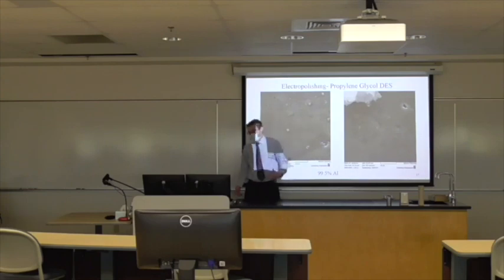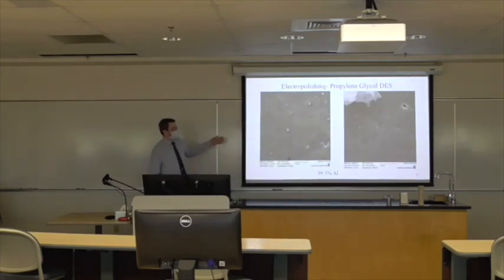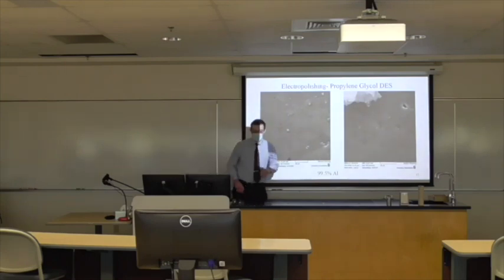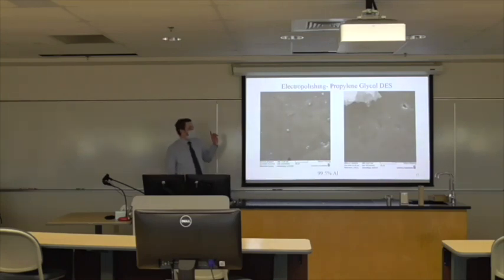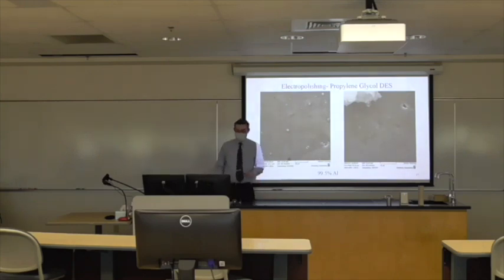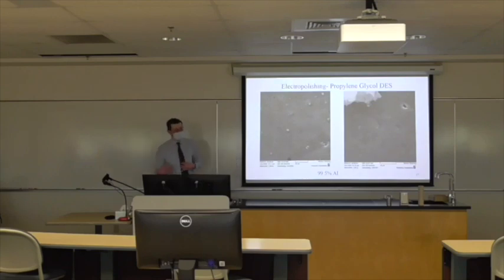Now this polishing, although there are still some defects, you could compare to the Brytal electropolishing method or the ethylene glycol electropolishing. There are still defects and it still works. Now, because the conductivity is lower, in general you would need more time for the same polish as something that's higher. For the Brytal electropolishing, you can get current densities up to about 100 milliamps per square centimeter. For the ethylene glycol DS, it's about 15 milliamps per square centimeter. But for the propylene glycol, it's 8 to 6 milliamps per square centimeter. So a lower current density means we're going to need longer time to make it work. With longer time, you would expect some of these defects to go away as well.